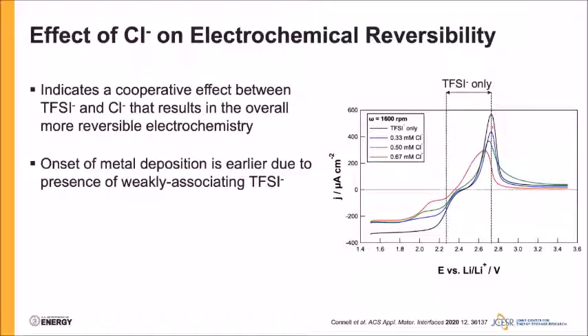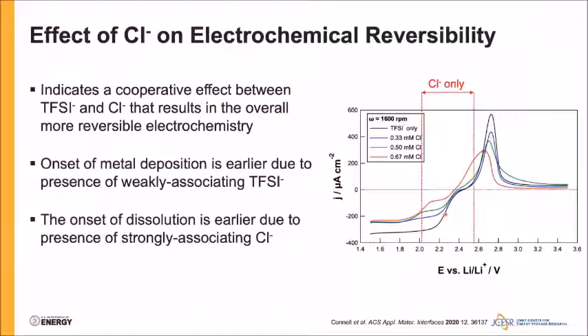Why we believe the deposition is able to initiate earlier is due to the relatively weaker association strength of TFSI with the zinc cation. And so it essentially takes less energy to desolvate zinc from a TFSI-rich coordination relative to chloride. If we look now at the chloride-based contribution to the voltammetry, we see, again, metal deposition initiating at higher overpotential, but the dissolution initiating at lower overpotential.